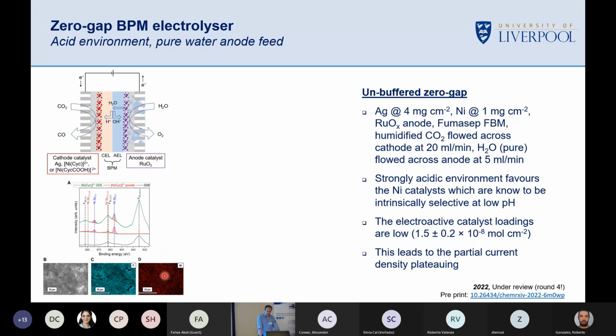The amount of nickel catalyst that's active is tiny compared to the amount we deposit. That's mainly because we deposit currently with someone with an airbrush spraying it, and half of it goes across the bench. It's also got a very low electroactive coating loading. We've tried to put carbon fillers in to improve it. It doesn't. I'll come to that in a second. So there's only about 10% of the catalyst actually active, but it's still enough.